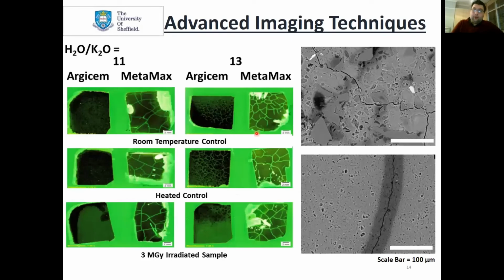Here we can see the heterogeneous structure I mentioned earlier, and why it would be really difficult to analyse this pore structure. What I'd like to do is some micro CT analysis, which I've actually got booked in for next month, to really focus down on the pore structure and see if we can see changes in the actual porosity of these samples.